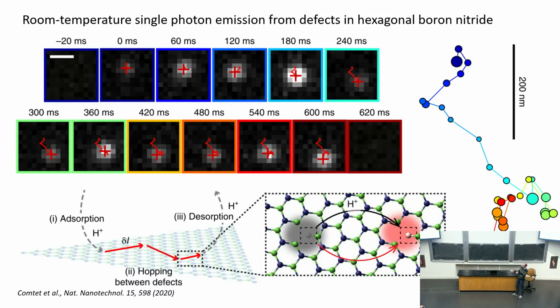So here is the picture that is suggested. We have this 2D material here with defects. We have a proton coming in that makes a dark state of an emitter bright because it couples, covalently bonds for some time, or it attaches for some time, and then it leaves. And you can basically see this hopping. You can trace this as a function of time on the surface. So you can reconstruct sort of these paths.